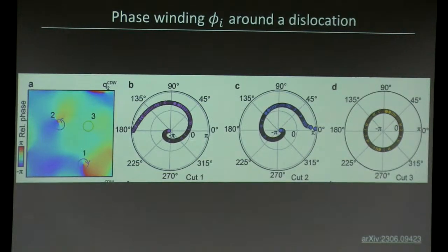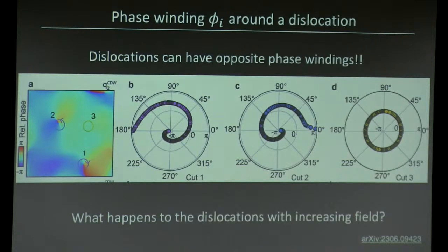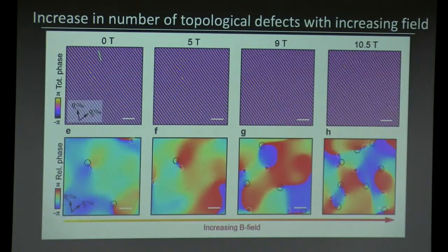Now we can look at what happens in a magnetic field. This is a series of inverse Fourier transforms of one of the 3 components of the CDW with increasing field. You can see with your eye that the number of point dislocations is increasing as you increase field, and in this relative phase map that the number of these phase windings is increasing. Interestingly, the colors here represent the direction of the winding, and you can see that these phase windings come in pairs.